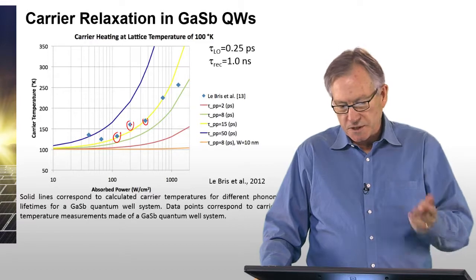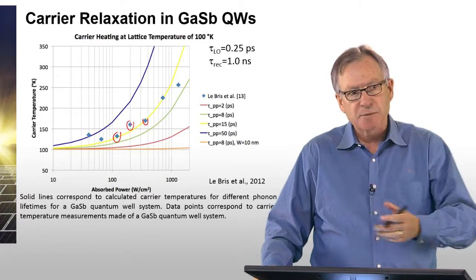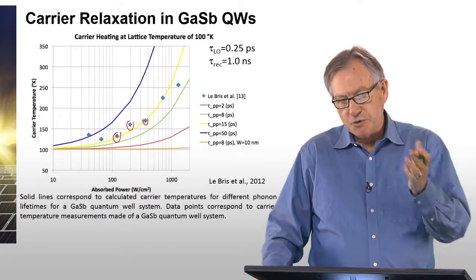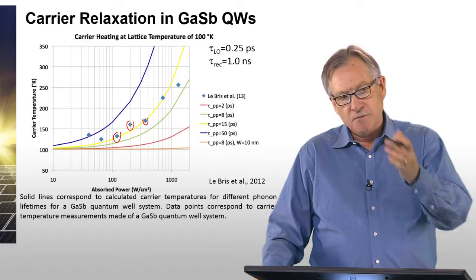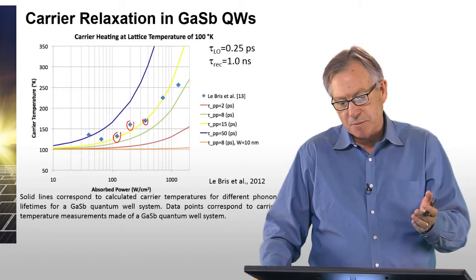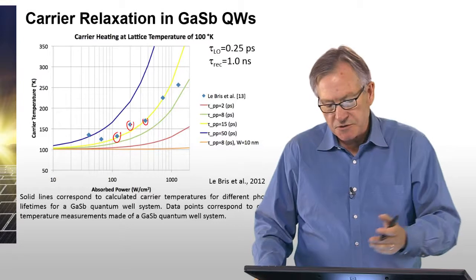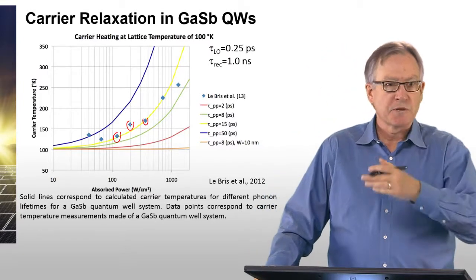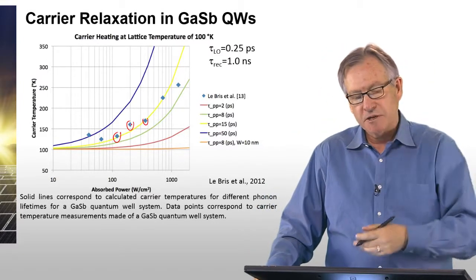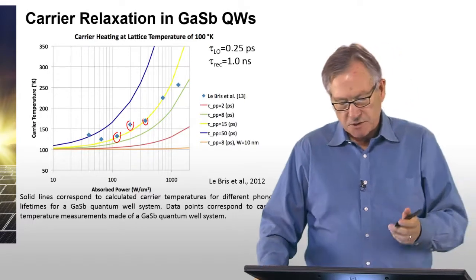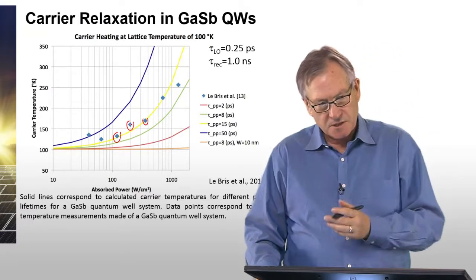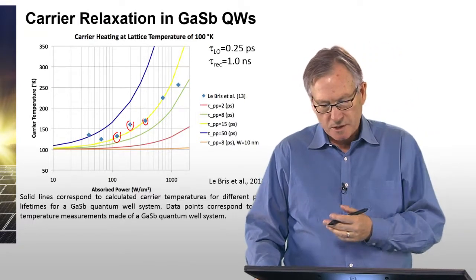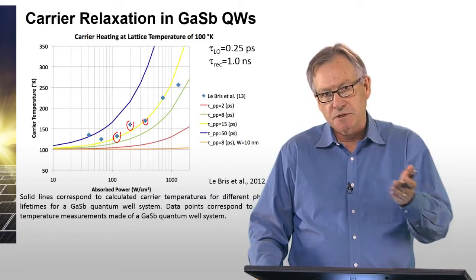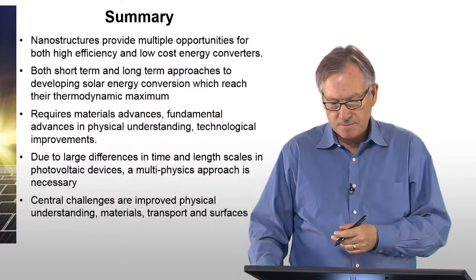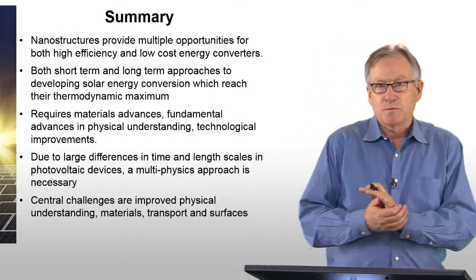So this shows at least that you can get some enhancement of the temperature that would be useful for hot carrier solar cells. Unfortunately, at this point, what you need is a temperature that's closer to 1,000 degrees Kelvin in order to really see the benefits of the energy selective contacts. And so at this point, it's still a research topic. It's not so far a practical solar cell, but it is a solar cell like the other ones that has a pathway to basically achieving high efficiency.